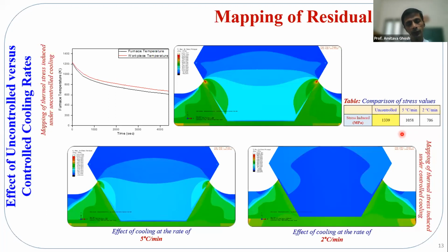So when we cool down from a temperature which is 1000 degrees centigrade, it takes quite a lot of time in the laboratory. It takes almost 7 to 8 hours to complete one brazing cycle. Of course, because it's a radiative heating, because the entire environment inside the hot zone is under vacuum, the only mode of heat transfer is the radiation. But still we can control the cooling rate, because you can suddenly switch off the heat input to the furnace, or you can still allow the heat input to be there to some extent, so that the cooling rate can be controlled. Of course, we have seen that the cooling rate also has a tremendous effect. If the cooling rate is high, the stress level also will go high, which is not good.